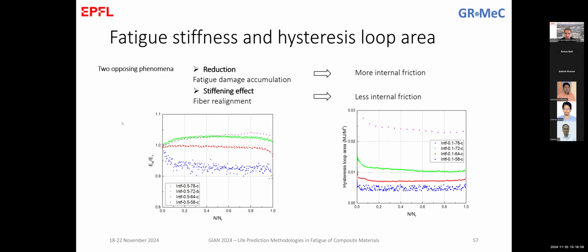And what we can see here in the stiffness, and what we expect for stiffness, is a behavior like these blue symbols that we have here at the 58 stress level. We see the normal, expected stiffness degradation. This is a trend that we know we should have for stiffness degradation, so this is perfectly correct for us.